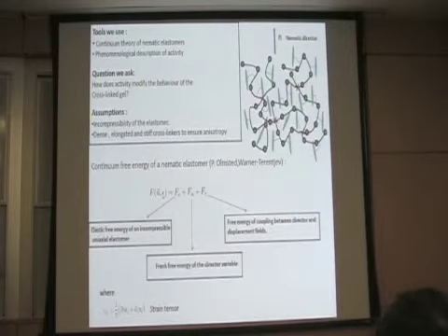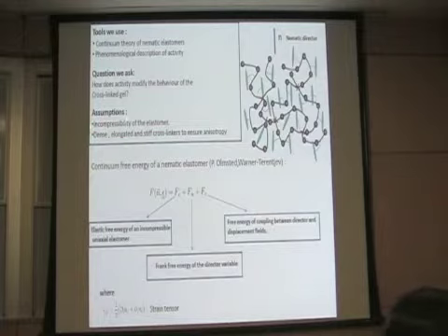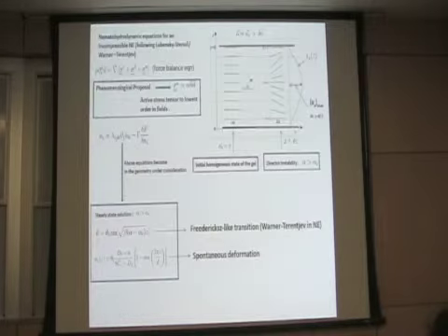The term that plays a role is the coupling between the nematic field and the strain field, which defines the deformation of the elastomer. The main assumptions that go into the theory are the incompressibility of the elastomer, a particular geometry, and dense, elongated, and stiff crosslinkers so that anisotropy develops in the network.